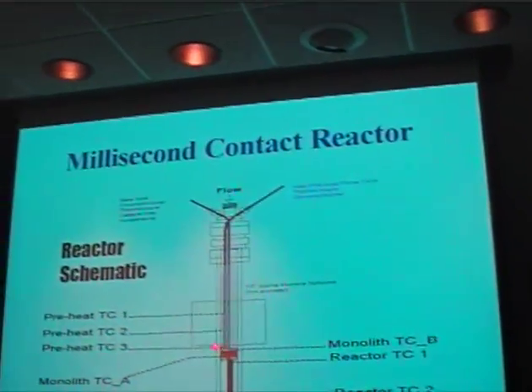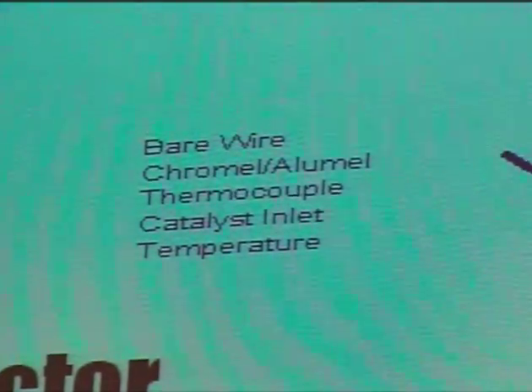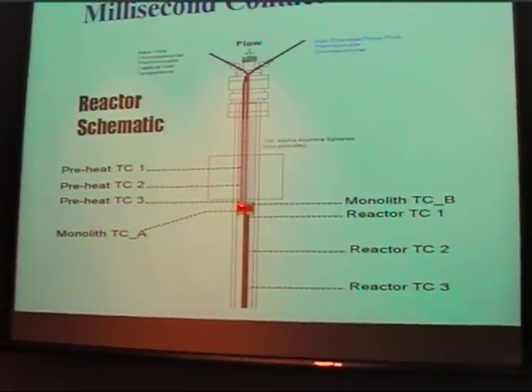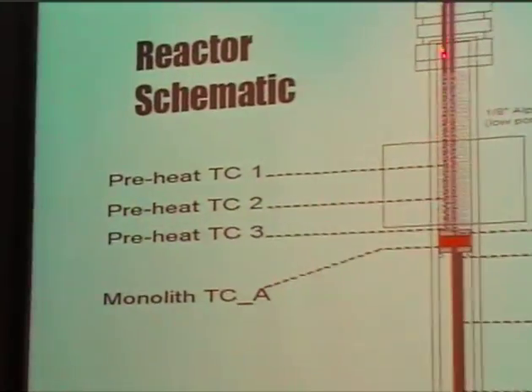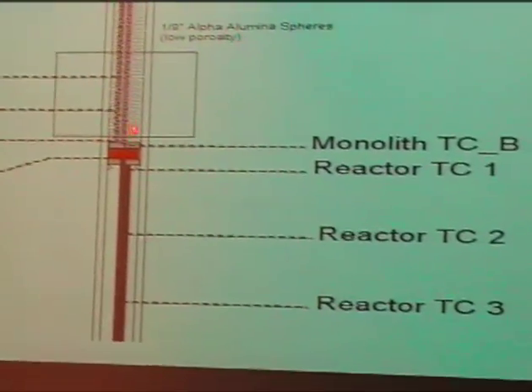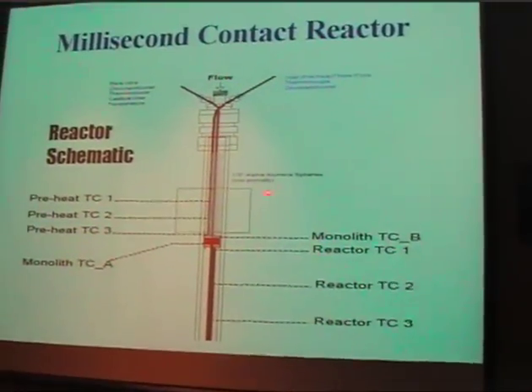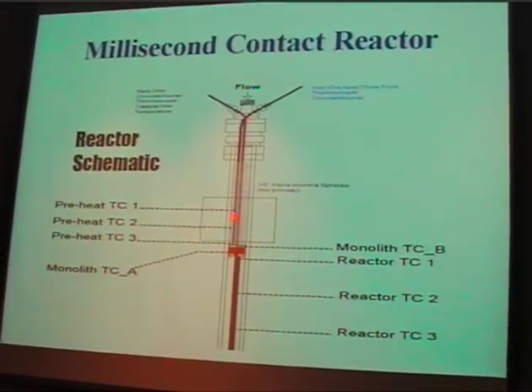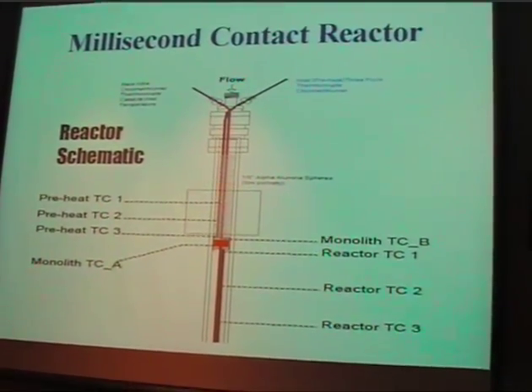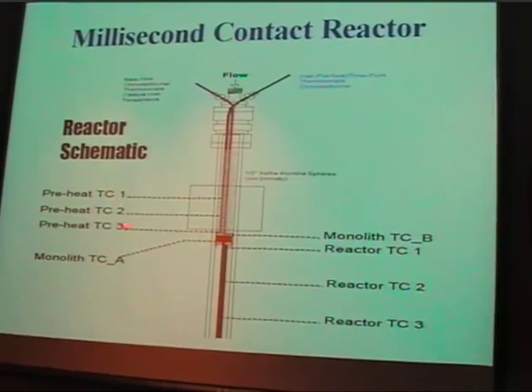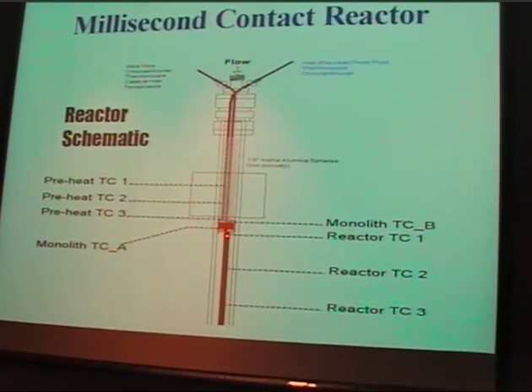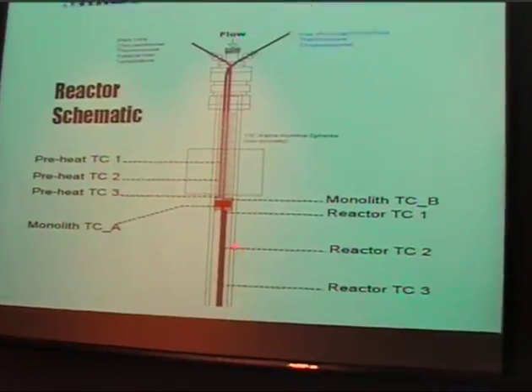So we packed our catalysts as a monolith shown here, and it's sandwiched in between two ceramic foams, and that is to help maintain the heat within the catalyst bed and prevent heat loss. The entrance feed would come in from above. We would have alpha alumina spheres to basically take up the dead volume and minimize the homogeneous reactions. We monitored a lot of the preheat area, and also right below the catalyst bed we monitored that temperature, and further down there's a quick drop off of temperature.